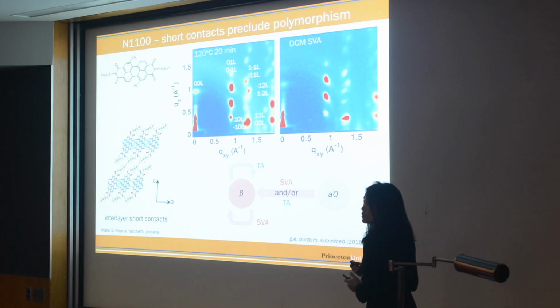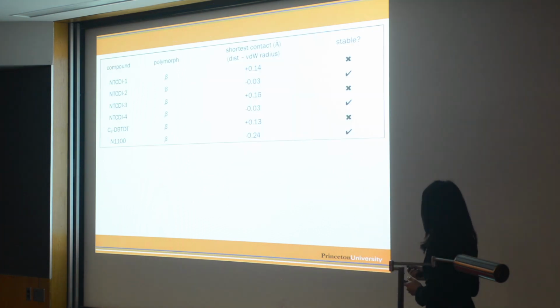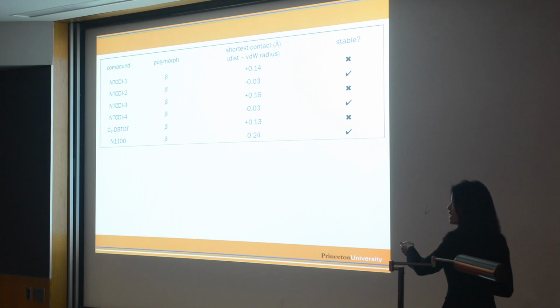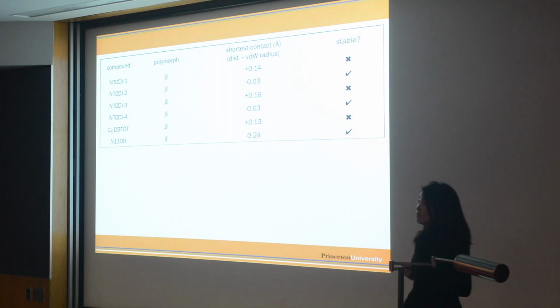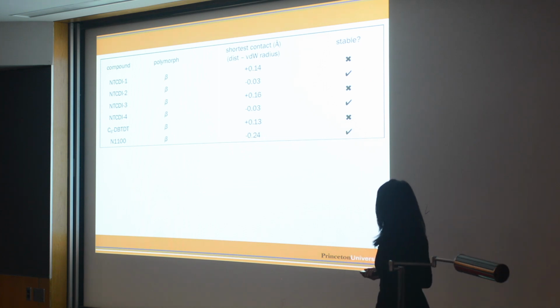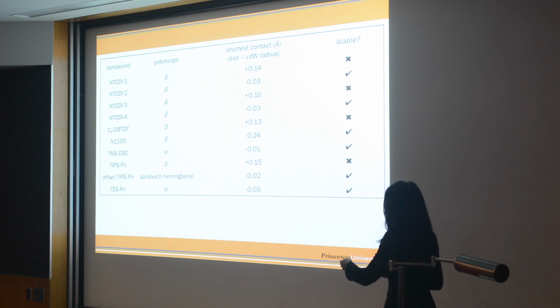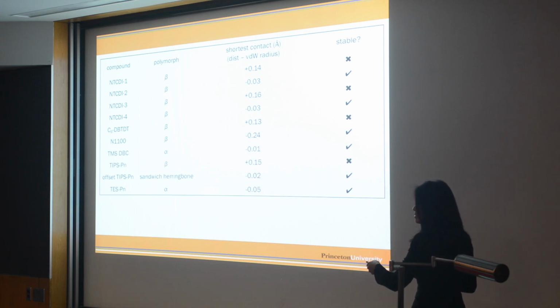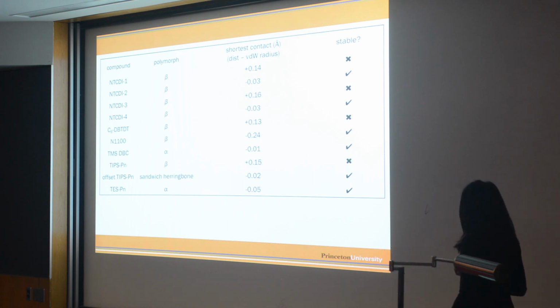Consistent with having these short contacts present between the layers. So we can add this. It's a negative number, and this polymorph appears to be kinetically stable. So I've added other organic semiconductors. The data is the same, right? So positive, it's not stable. Negative, it's stable. So it appears that the list goes on.